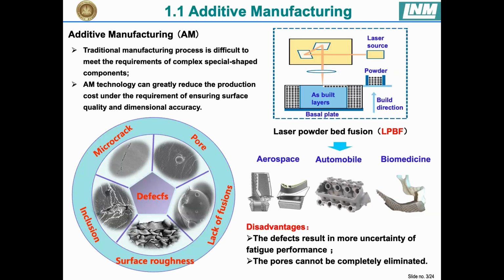Through the optimization of the process and the manufacturing and the post-treatments, defects like micro cracks, inclusions, surface roughness, and lack of fusion can be well eliminated, but pores cannot be entirely eliminated due to the rapid cooling speed, which causes gas to be unable to escape from the as-built component in time. Therefore, it is critical to further study the influence of pores on the fatigue performance.